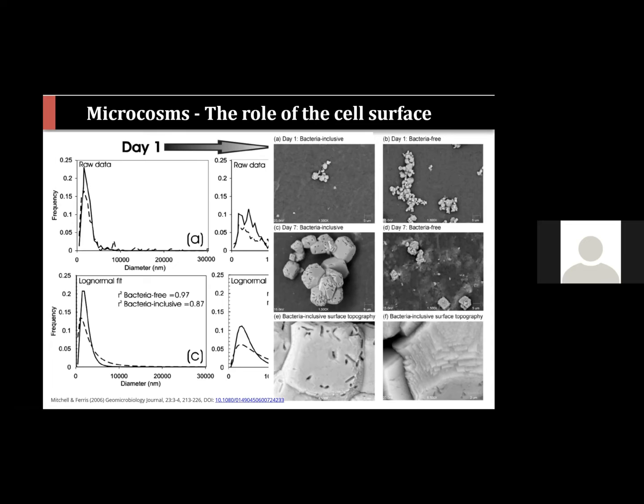So it really seems that while we can show from the initial nucleation phase that the cell surface is important, we go from a cell interaction process initially, where we get nucleation on the cell surface, ultimately to a solution that's really dominated by reactions in the bulk solution, where we're getting growth on established crystals as a route to the main increase in crystal mass within these systems. So over time, it seems that there's less influence of the cell surfaces.